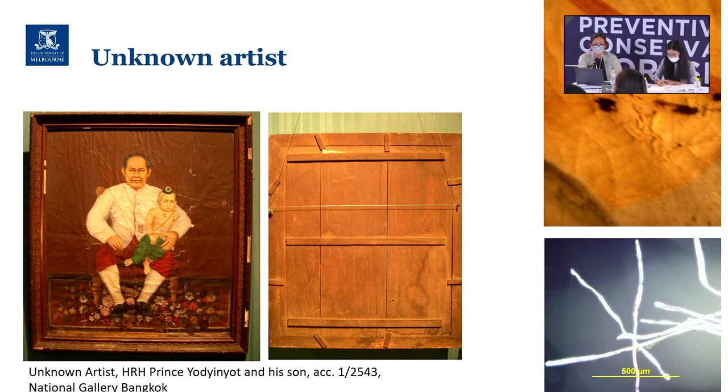So in this case you can see some analysis where we've identified it is a cotton canvas under the microscope, and cotton we know with time degrades much more quickly than other types of fibers and so it becomes very brittle. So you have the brittle canvas layer in association with a layer above, which is a tempera type of material.